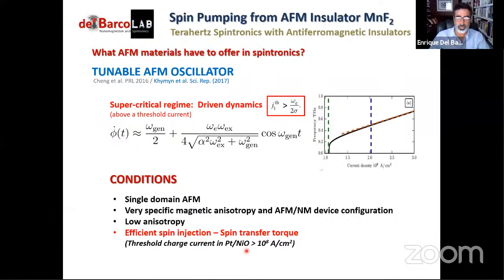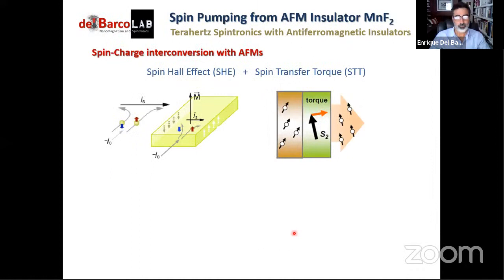Some quick calculations by the authors on platinum nickel oxide tell us that they need 10^8 or more amps per square centimeter flowing through platinum in order to overcome this threshold. And this is actually a very high current that is basically going to melt platinum. So we're looking for other variations of symmetries, materials, etc., in order to make this more efficient with lower currents. I will continue with my introduction. I told you it was going to be a long introduction.